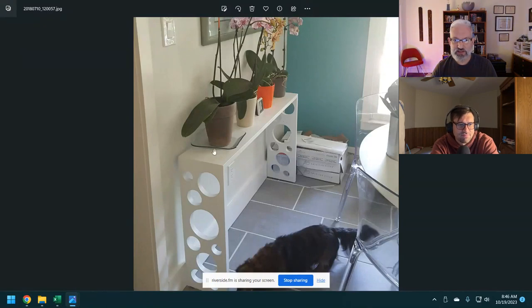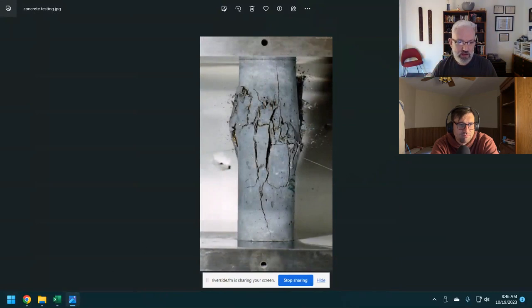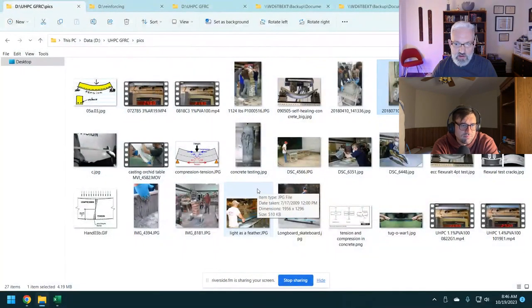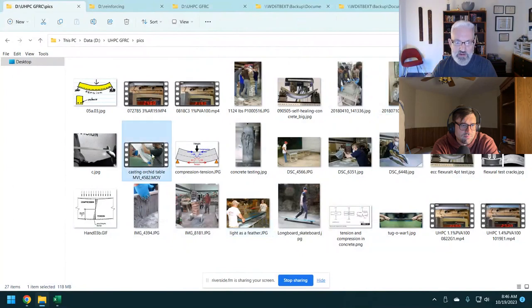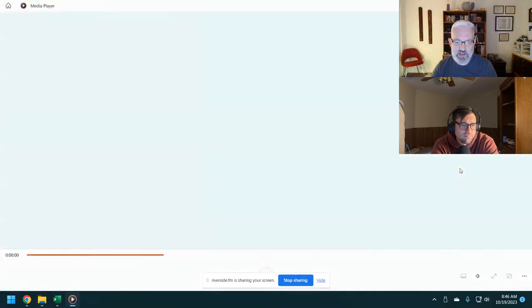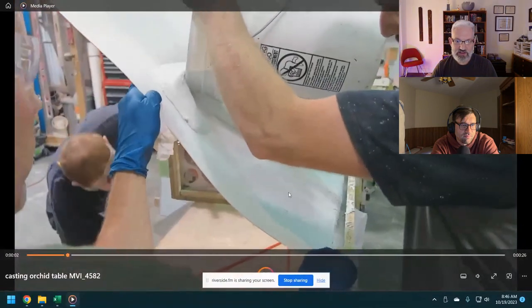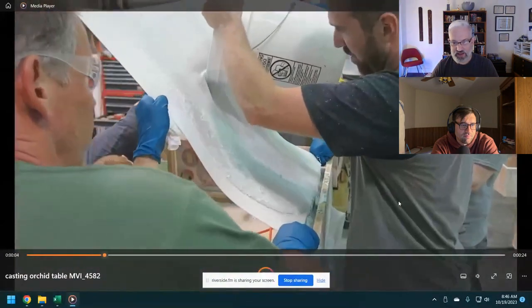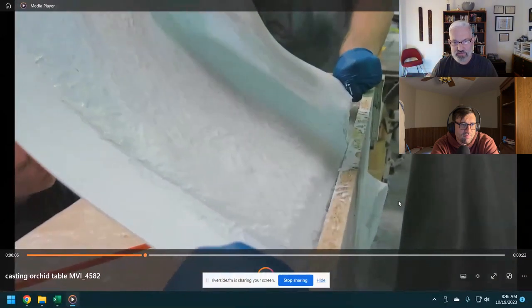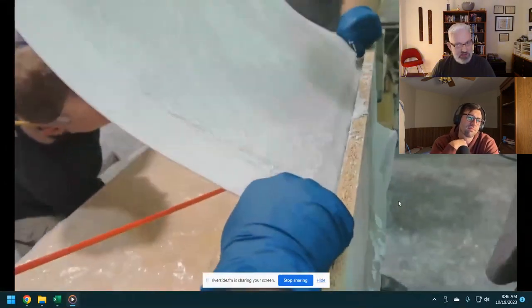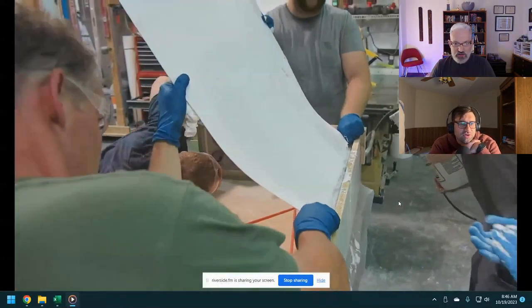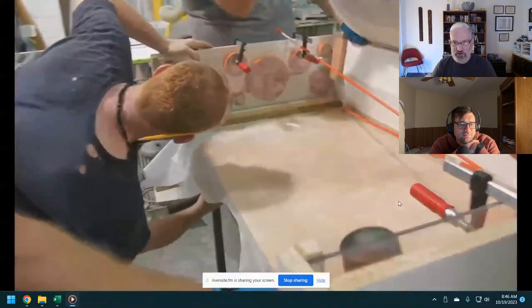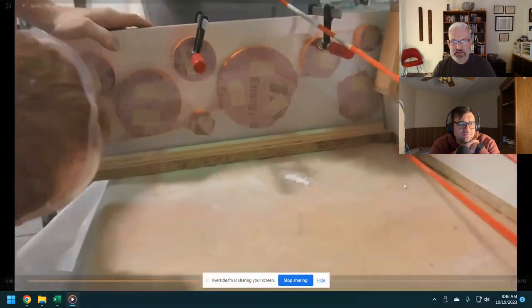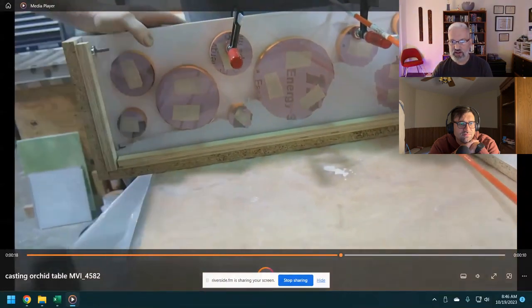And the way I cast it, this is all direct cast GFRC. I'll come back to that in a second. Okay, here we go. So this is casting in class. The form's laying on its edge, and we're casting from the backside, and that is a conventional. That is some lovely fluid concrete, Jeff. Fluid, 3% load of fibers, and this is kind of where a high fiber content breaks down.